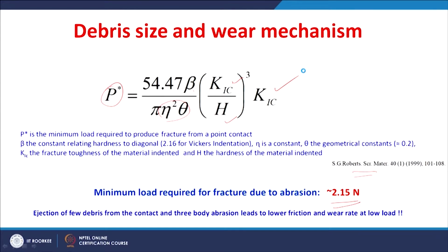So, all this happens at a lower load of 2 Newton; a minimum load of 2 Newton is sufficient for the fracture to occur. Once this fracture occurs, debris particles are in contact and a few of them are ejected out. That leads to a lower coefficient of friction, and because of the easy rolling, it gives lesser wear as well. Whereas in the case of a higher load, we saw tribochemical wear dominating.